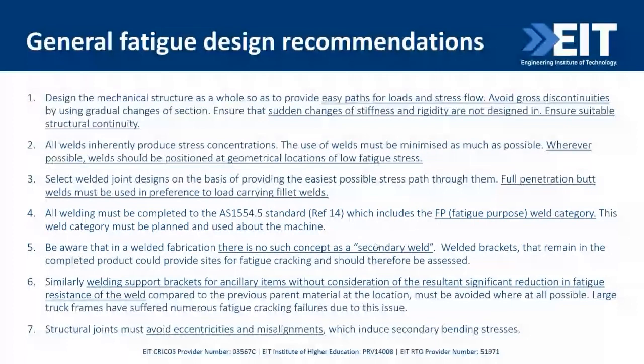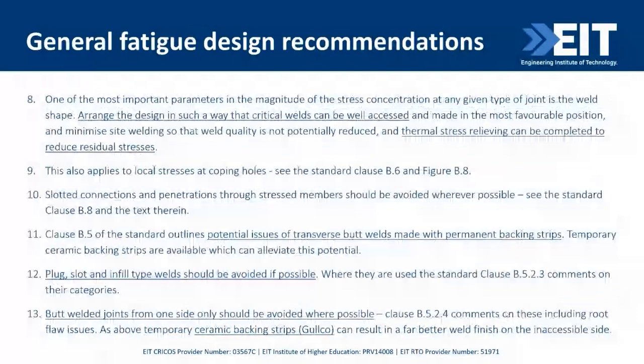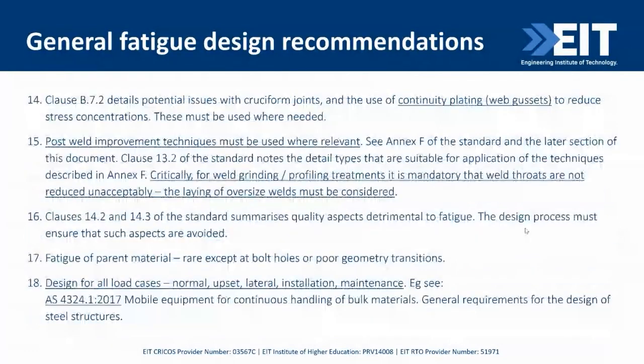Don't weld on those because you're reducing the fatigue resistance of that parent metal high strength steel by a factor of 5 as soon as you weld a bracket onto it. And it's the same with mine dump truck chassis. Similar things have happened. So that's all fairly obvious, and I hope the case studies will explain that well. Load cases, as I've said before, are critical. The AS 4324 is the mobile equipment for continuous bulk handling code, and it goes through load cases for that equipment extremely thoroughly. And if you can get a copy, or even the earliest version, it'll show all those load cases outlined, and it gets you thinking about what the machine is going to see in service.